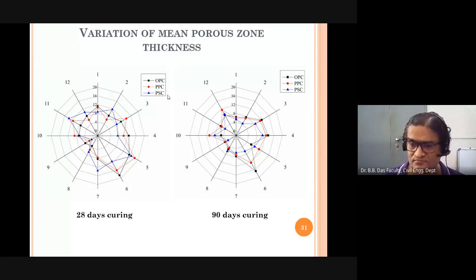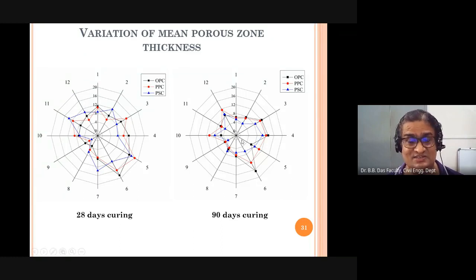Now come to the 90 days. With more prominent curing, the space between the steel and concrete is reducing, which we can see here. Still the PSC band is much lower than the OPC and PPC. So PSC has more stability if you do good curing.